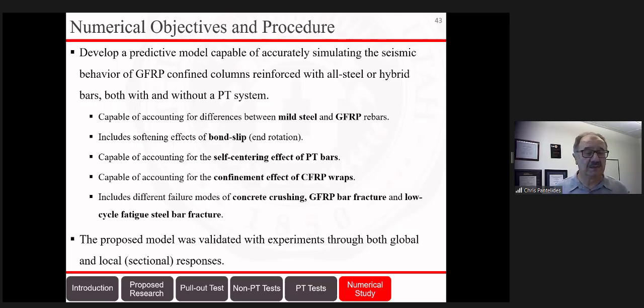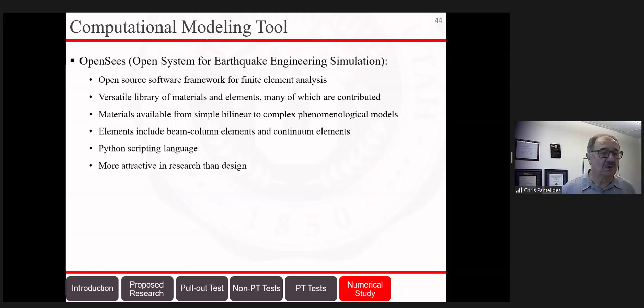We want to make sure that we capture the failure modes, which is the concrete crushing, the fiberglass bar fracture, and low cycle fatigue failure of the steel bars, which causes their fracture. So we tried to validate the model that was developed for these tests. We use OpenSees, which is an open source software.